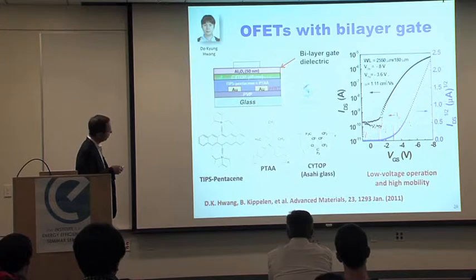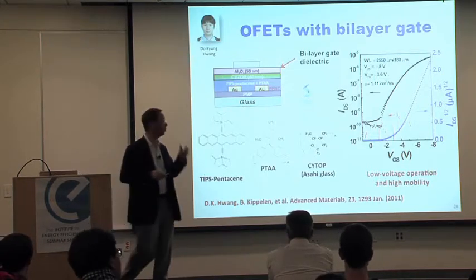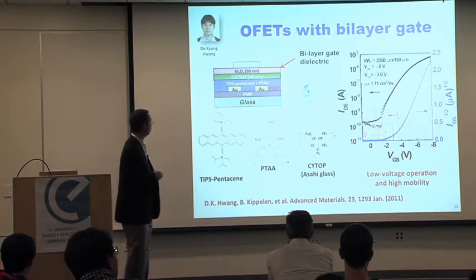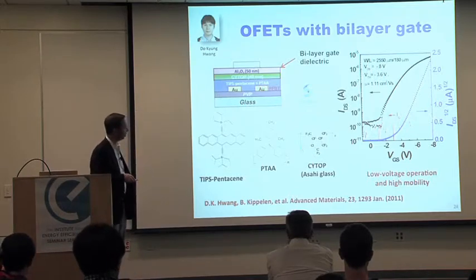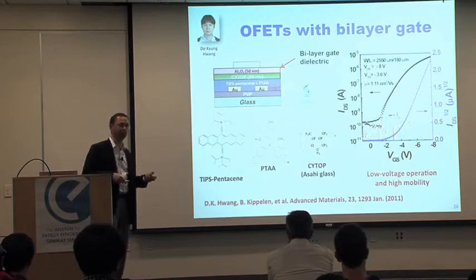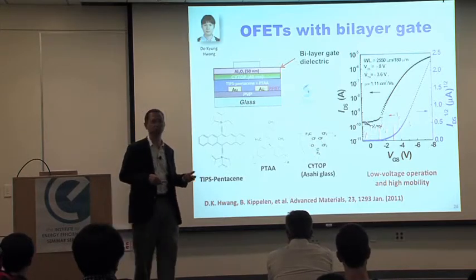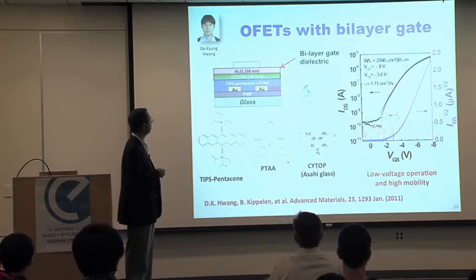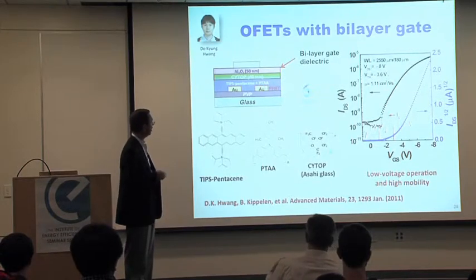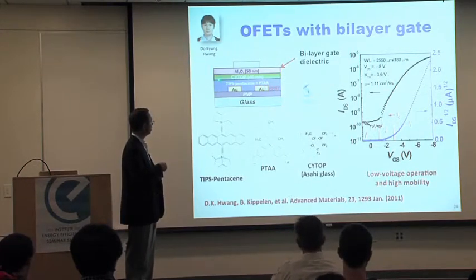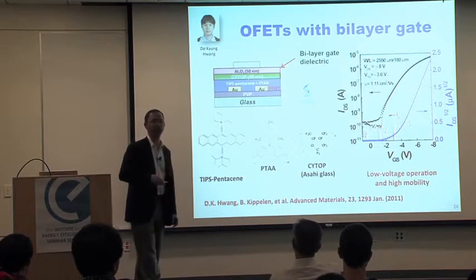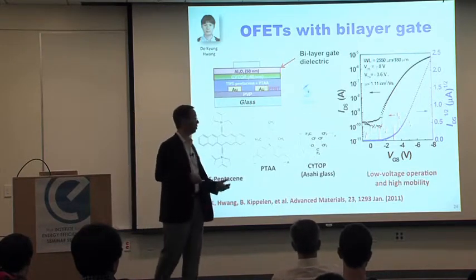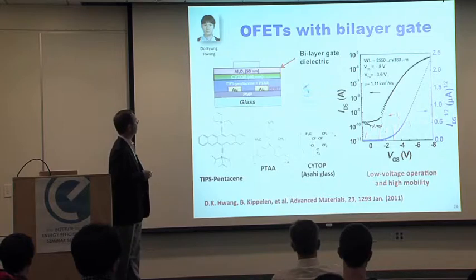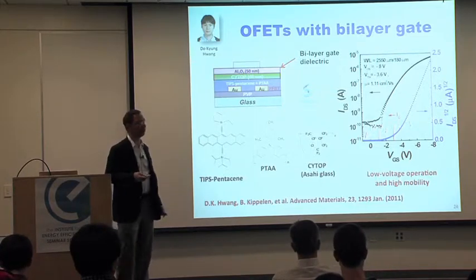And then we spin-coat first a thin layer of a perfluorinated polymer, such as Cytop. The choice for the perfluorinated material is that usually these materials are processed from solvents that are orthogonal to the conventional solvents that are used to process the semiconductor. So when you spin coat that layer on top of the semiconductor, you get a very clean and sharp interface with very few defects, which is important for the stability of the transistor. But Cytop itself has a fairly low dielectric constant, so that's the problem.